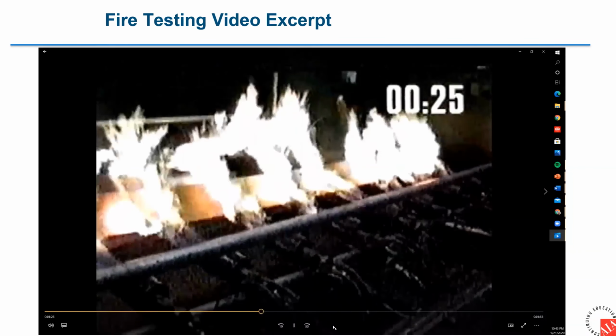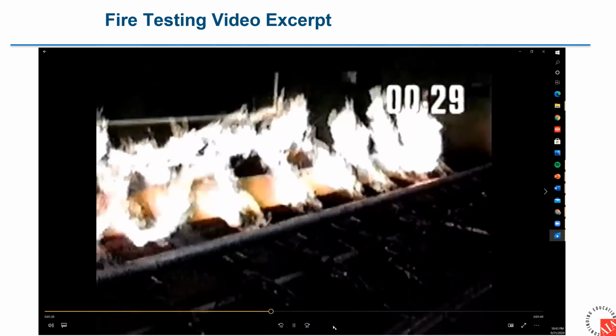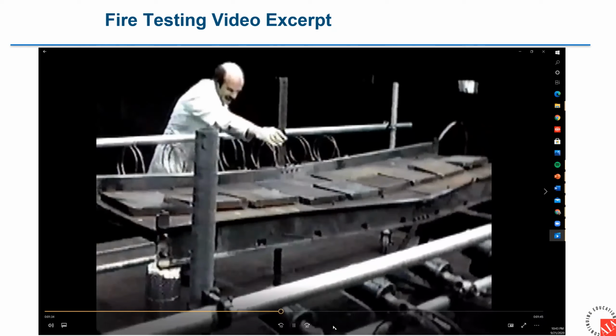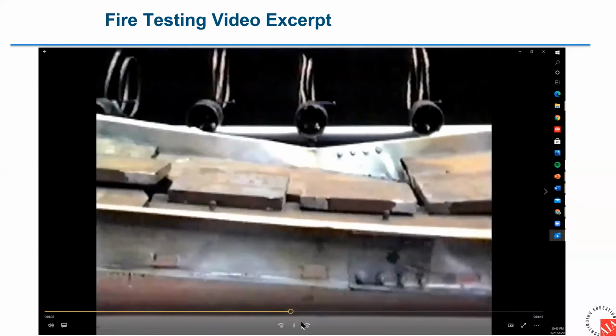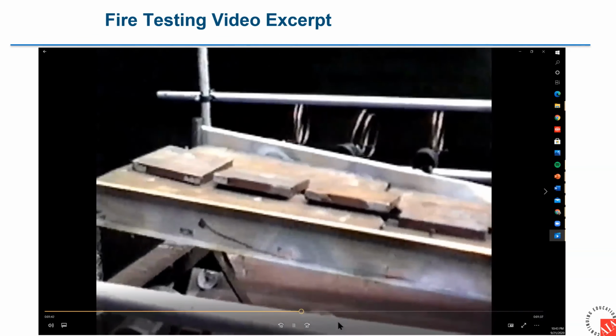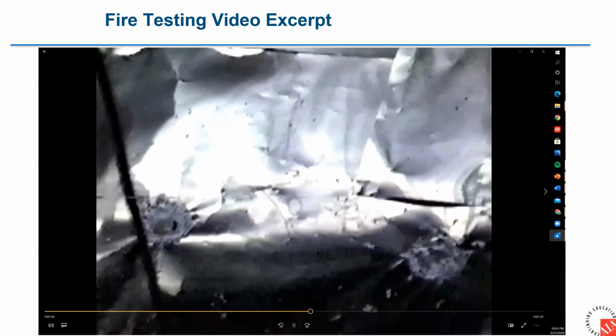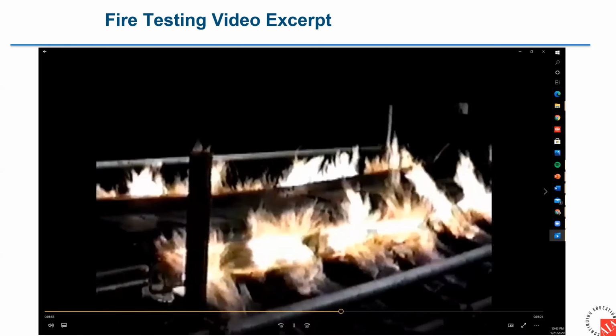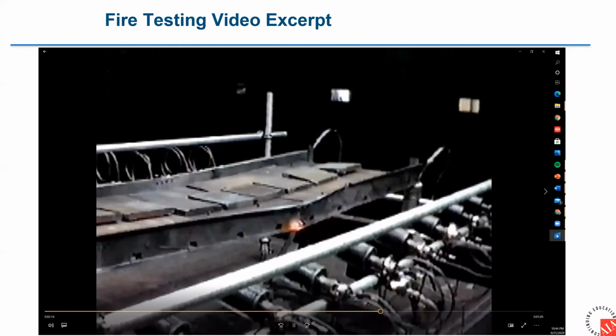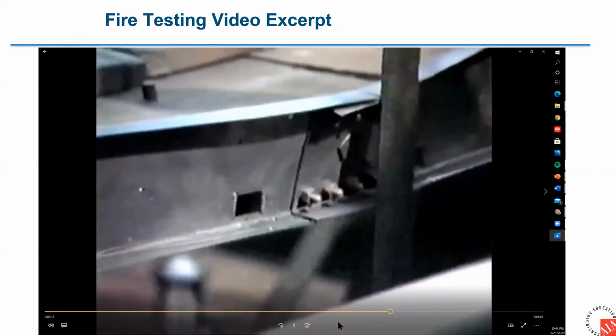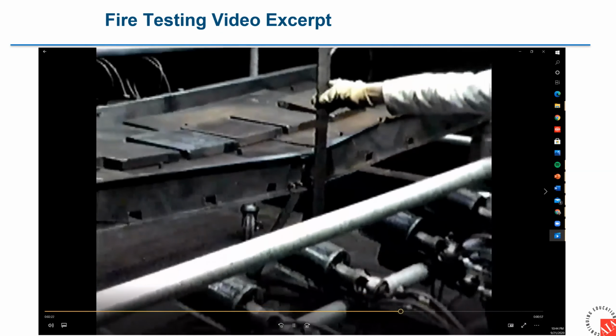Smoke and fume emission were also noted during the test. GRP is FRP. The galvanized carbon steel withstood the heat for the full 5 minutes of the test. However, zinc globules were observed dropping during the test, a potential additional hazard. Stainless steel satisfied all the criteria, and at the sponsor's request, the test was continued until the gas supply ran out, during which time the average flame temperature exceeded 900 degrees centigrade for 30 minutes and 1000 degrees for 14 minutes. Deflection was measured after 45 minutes and was only 80.5 millimeters, compared with 166.5 millimeters deflection of galvanized.